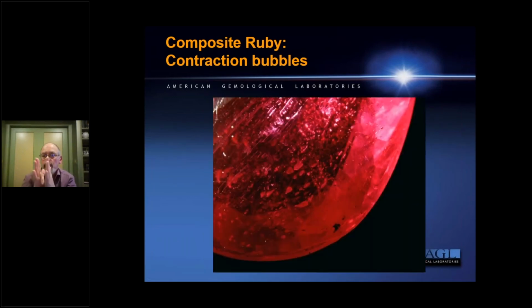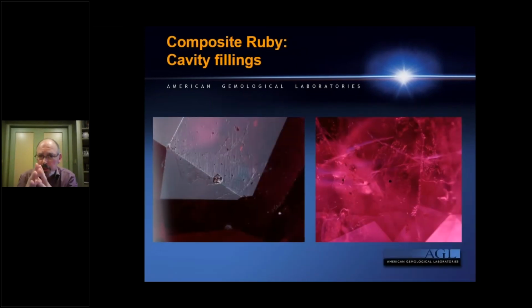Now, when they're occurring more on fractures, so they've got boundaries of corundum, these contraction bubbles get flattened. So you'll see flattened contraction bubbles. Everything you see in here, these are all flattened contraction bubbles, but again, representing areas where it's a larger volume of high lead content glass. Cavity fillings are very, very common.